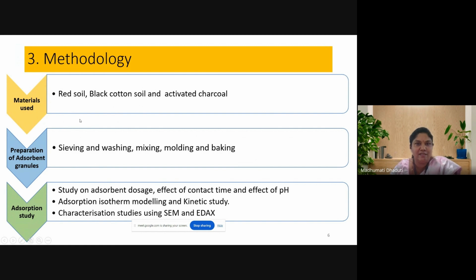So the methodology includes collection of the materials, and then the second step is preparation of adsorbent granules. Here, how it was done: red soil and black cotton soil were sieved through a 75 micron sieve, and finally completely washed, and the washed water passing through the 75 micron sieve was collected in a container and sedimented there. The clear supernatant was taken out, and the sediment, which is the finer clay particles settled at the bottom, was dried for 24 hours in an oven at 100 degrees centigrade.